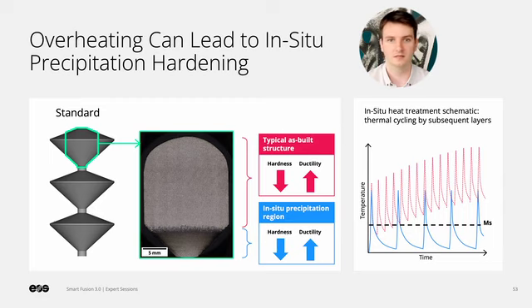We observed a very interesting effect when we analyzed the heat demonstrator built without Smart Fusion. While the middle and the top of the sample show a typical etching response for the as-built state, the unusually dark region above the thermal bottleneck caught our attention. A drastically different etching response like this usually hints at a severe change in microstructure. The reason for this altered microstructure is an in-situ heat treatment leading to local precipitation during processing.